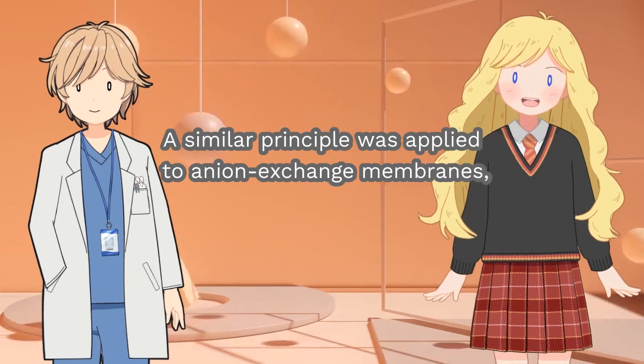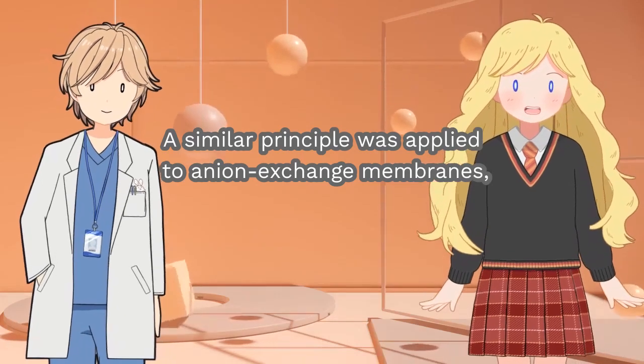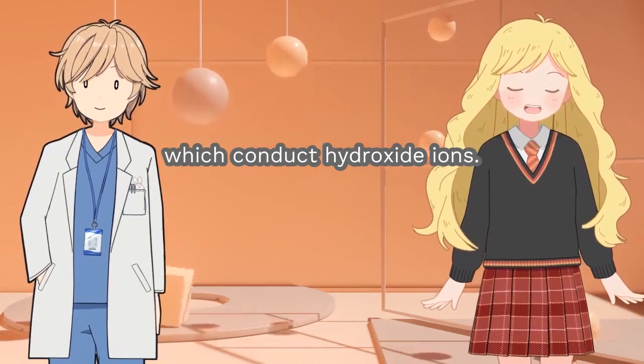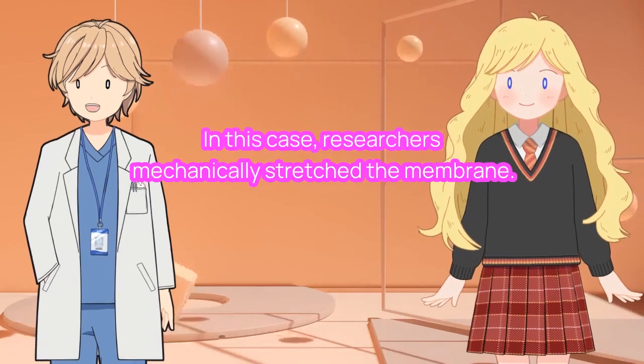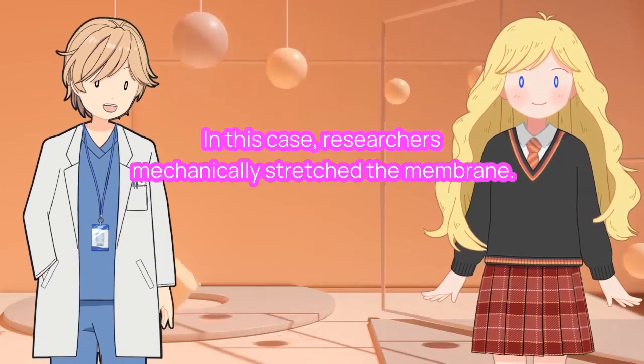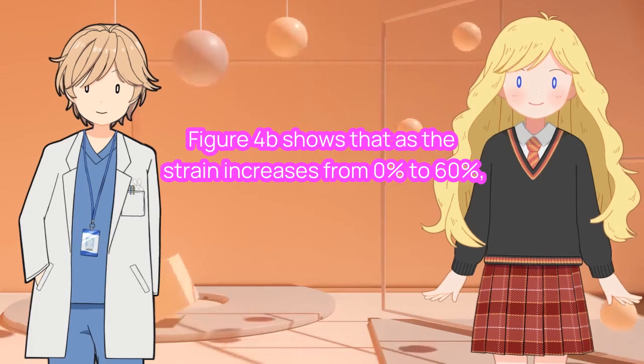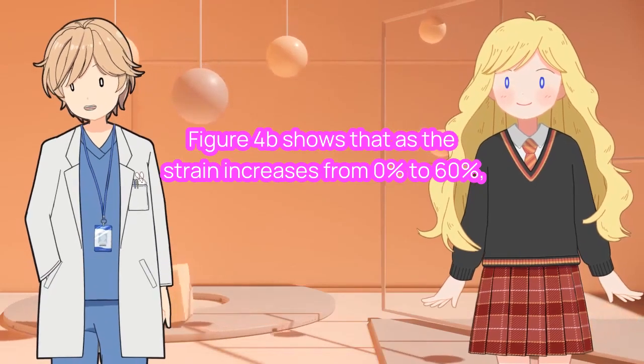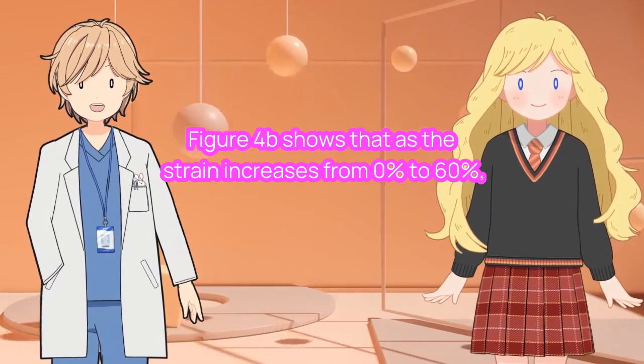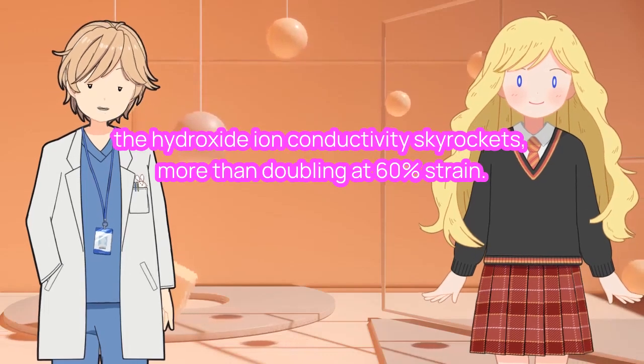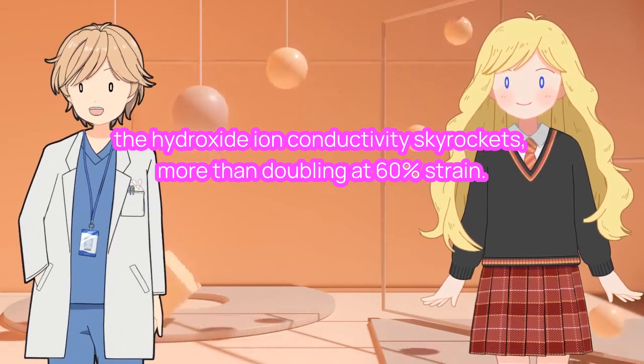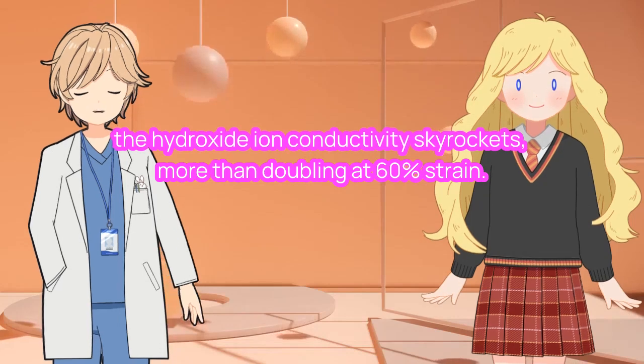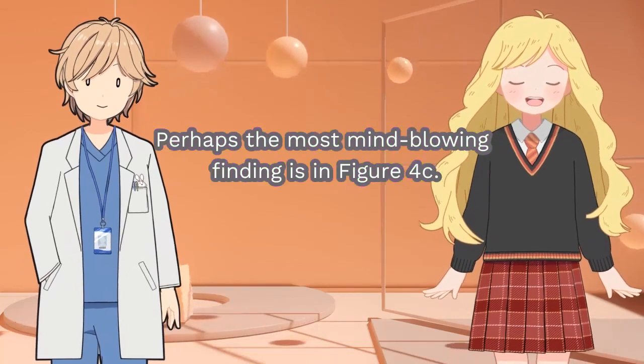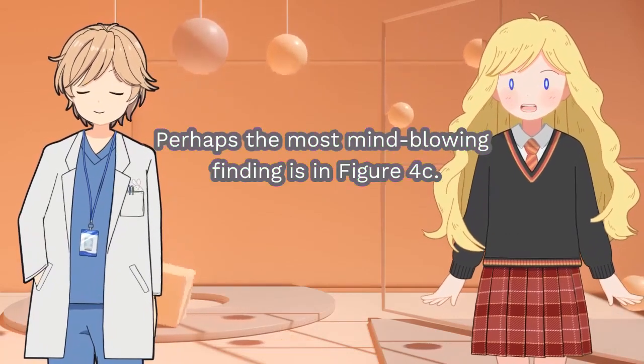A similar principle was applied to anion exchange membranes, which conduct hydroxide ions. In this case, researchers mechanically stretched the membrane. Figure 4b shows that as the strain increases from 0% to 60%, the hydroxide ion conductivity skyrockets, more than doubling at 60% strain. Perhaps the most mind-blowing finding is in Figure 4c.